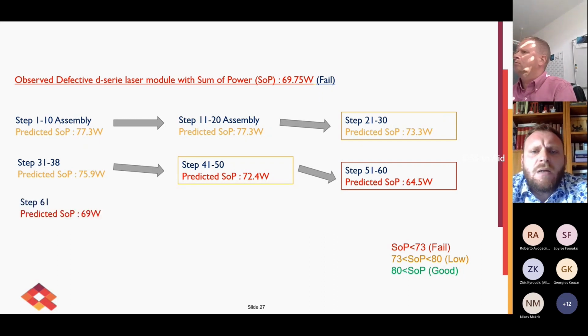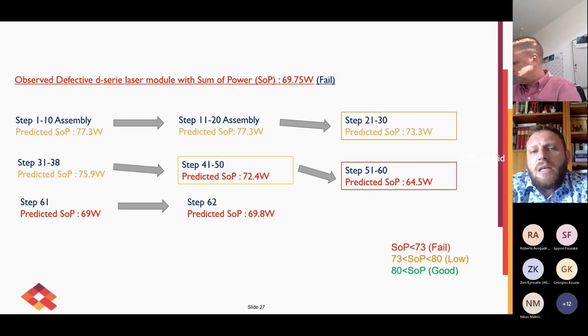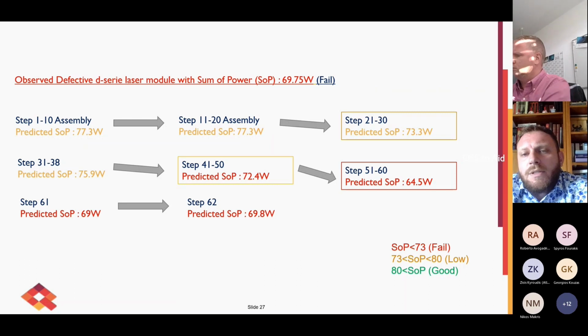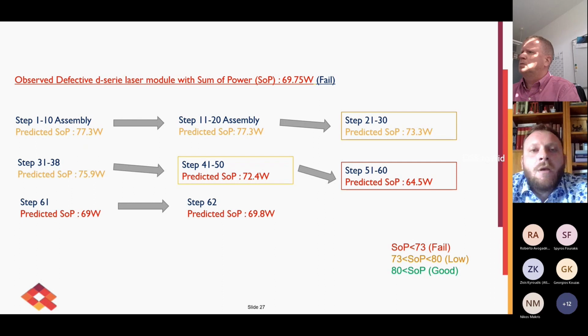And as you can see, okay, there is a rectification here now, probably because of the polarizer that boosted the power, and at the end we get the same predicted power as the actual pretty much. We predicted 69.8 where the actual was 69.75. So as you can see, from step 41 to 50 of the assembly process, you can say, okay, abort that module, save the material, save time, and save also energy.